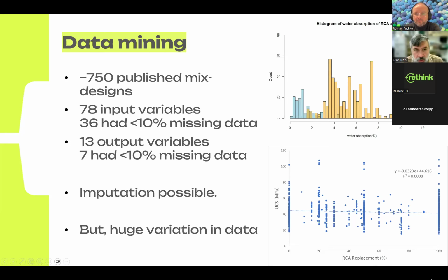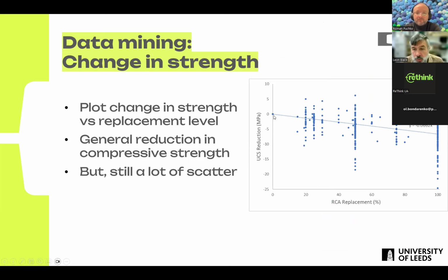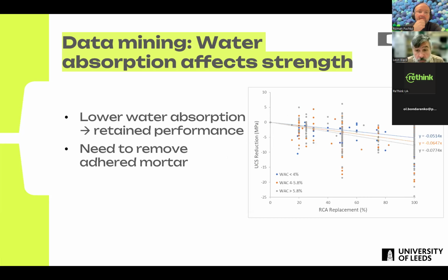Well, if we know that there is this loss in strength, we plotted the percentage replacement against the change in strength. And we can see here that there is a general reduction in strength versus the replacement, but there is still a lot of scatter in the data. And this is where having these other input data, such as, for example, the water absorption capacity, becomes important. We started to plot the reduction in strength as a function of replacement ratio for mixes with different water absorption capacities.